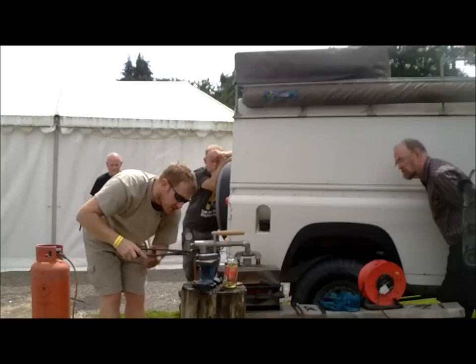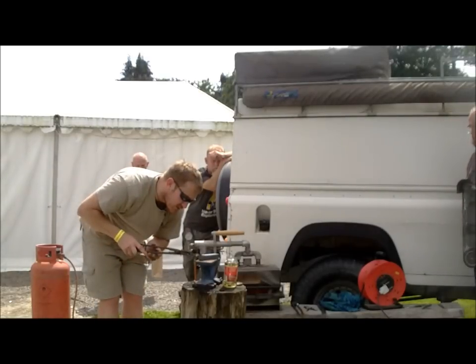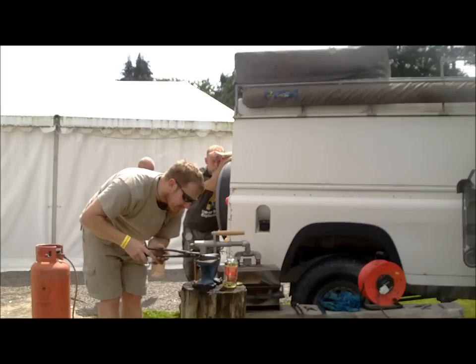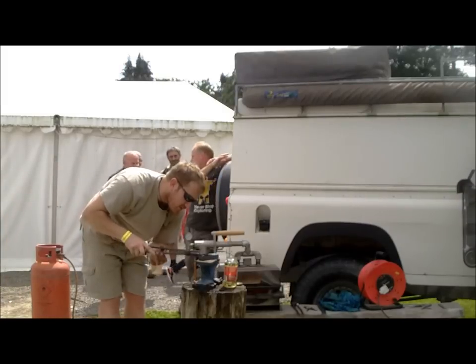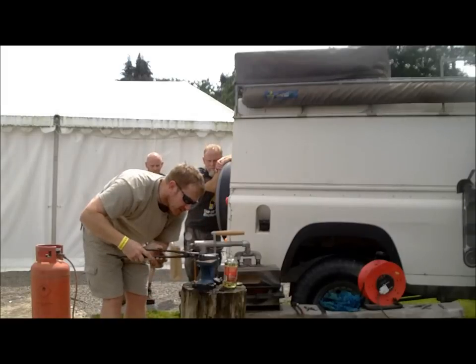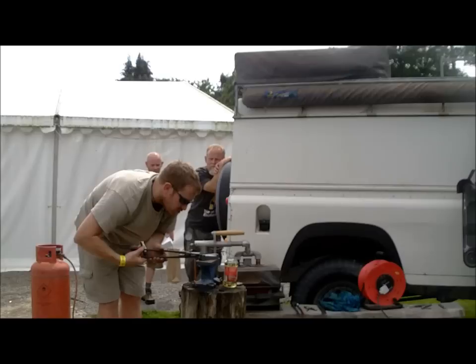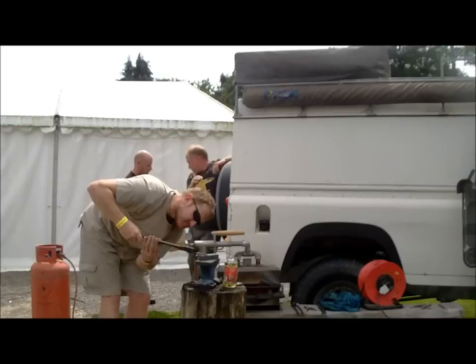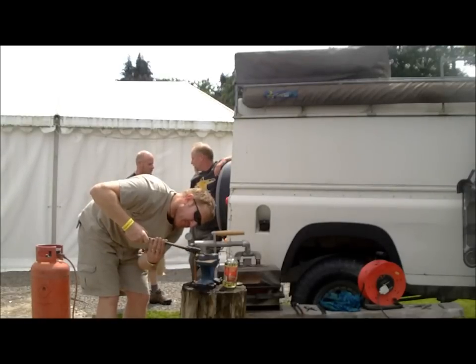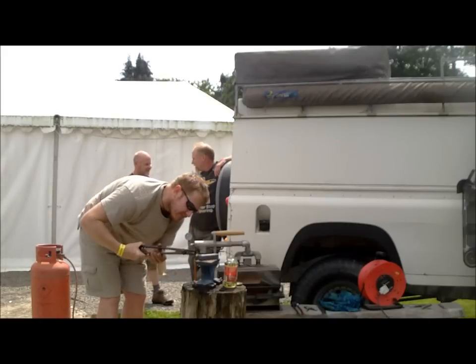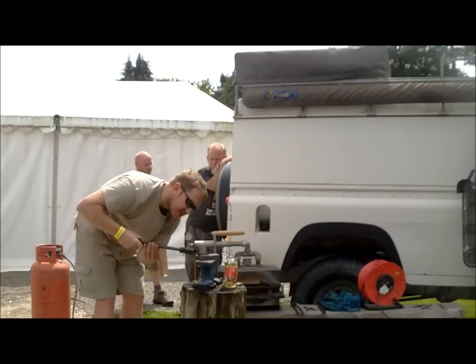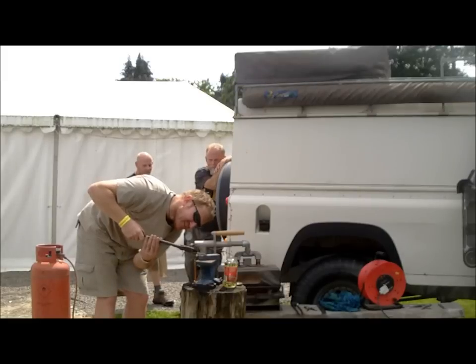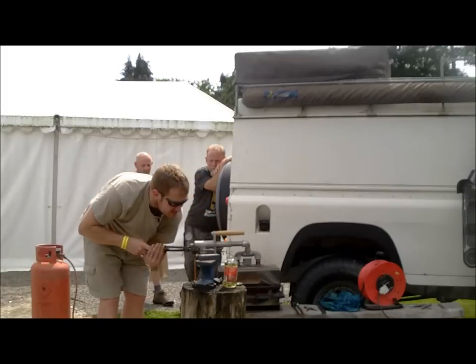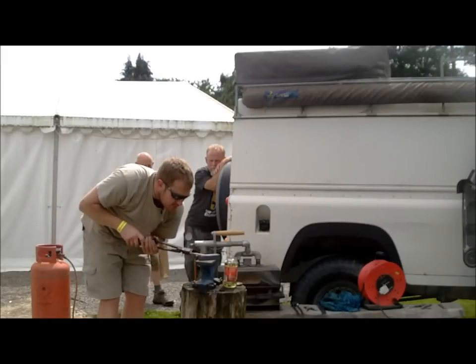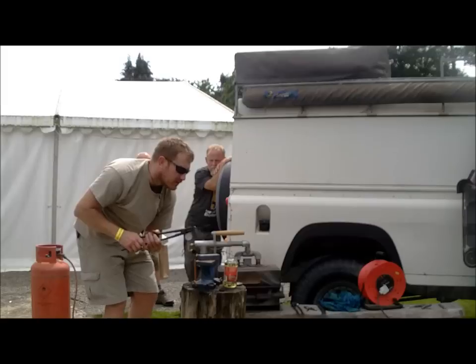So it's starting to transform, it's starting to go this straw colour, which is what we're looking for. You can lay it on the side if you want to transfer a bit more heat through into the thicker parts of the steel. I'm trying to soften that tang a little bit as well, so I'm placing a bit more heat on there. Even though that block of steel isn't glowing anymore, it's still got plenty of heat in it to temper this little blade. Can you see the colours yet? Yeah. That's why we brighten the steel, because if it was still all dowdy, we wouldn't actually see it.